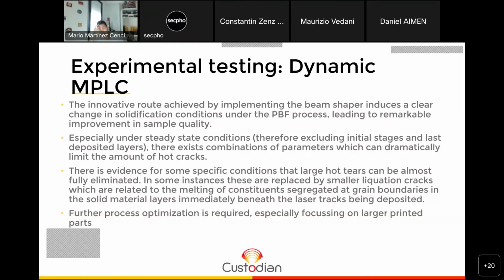So in some cases, these cracks are replaced by smaller liquation cracks, which are related to the melting of constituents segregated at grain boundaries in the solid material layers immediately beneath the laser tracks being processed. So all in all, there is a clear improvement of the process, but as you can see, further processing conditions optimization is required to achieve better results.